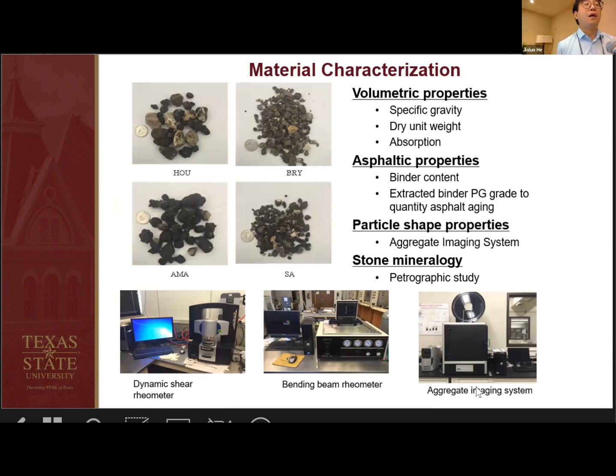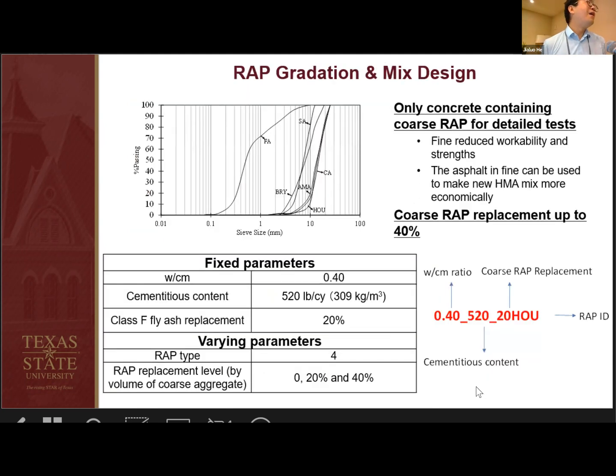So what we did is we collected a lot of RAPs from different Texas districts: Houston, Bryan, Amarillo, and San Antonio. Then we did a lot of material characterization. We did an aggregate property test. We extracted binder and did a binder evaluation using the PG grade system. We also did a particle shape and stone mineralogy test. Then we put our RAP in concrete as aggregate replacement, and we only replaced coarse aggregate with RAP, based on volume percentage.